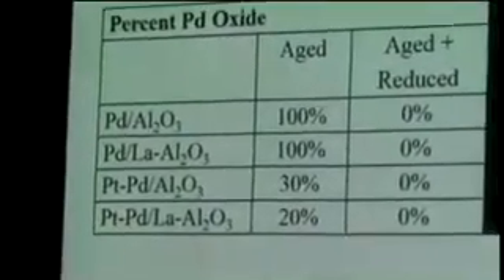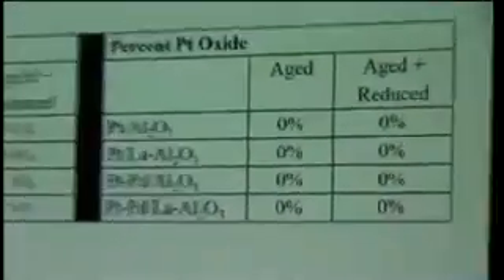Now if you go to the metallics, part of that palladium is reduced, and after reducing in hydrogen, it will reduce even further. So you can see that the palladium fractionates a little bit. There is a metallic phase and an oxide phase.